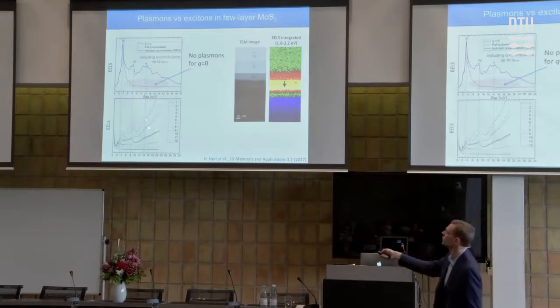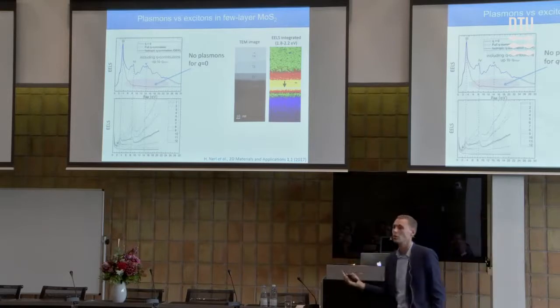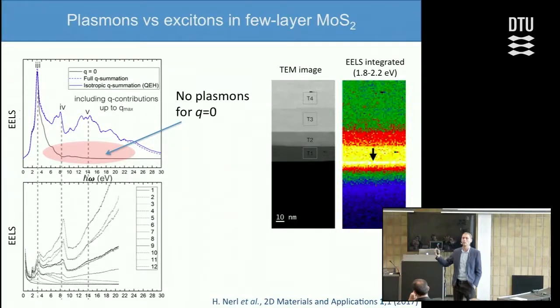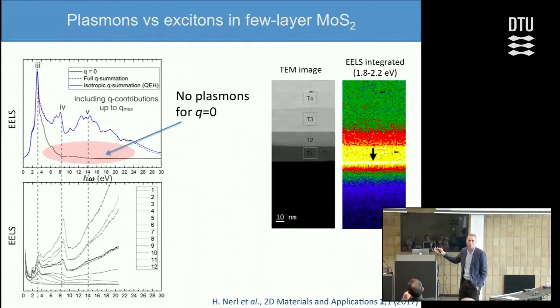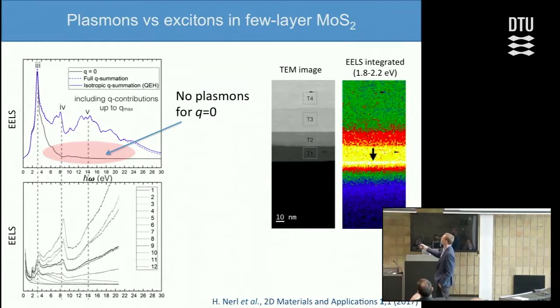All these features here are positioned where we would expect the plasmons to be, and we can infer that from plasmon calculations of bulk MoS2. But they don't show in our spectrum.